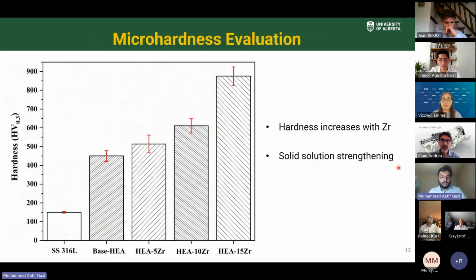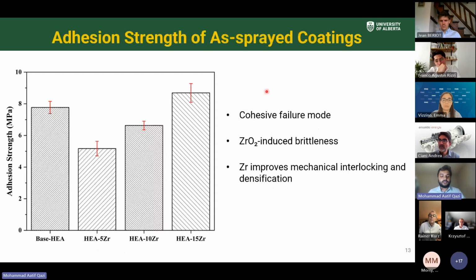Moving to the micro hardness evaluation, which shows an increase in the hardness with the increase in Zr reaching up to around 900 HV of hardness. Next, we have the coating adhesion strength test, which shows a cohesive failure mode with an initial drop in the adhesion strength at 5 weight percentage, but then an increase in the strength up to 15 weight percentage.